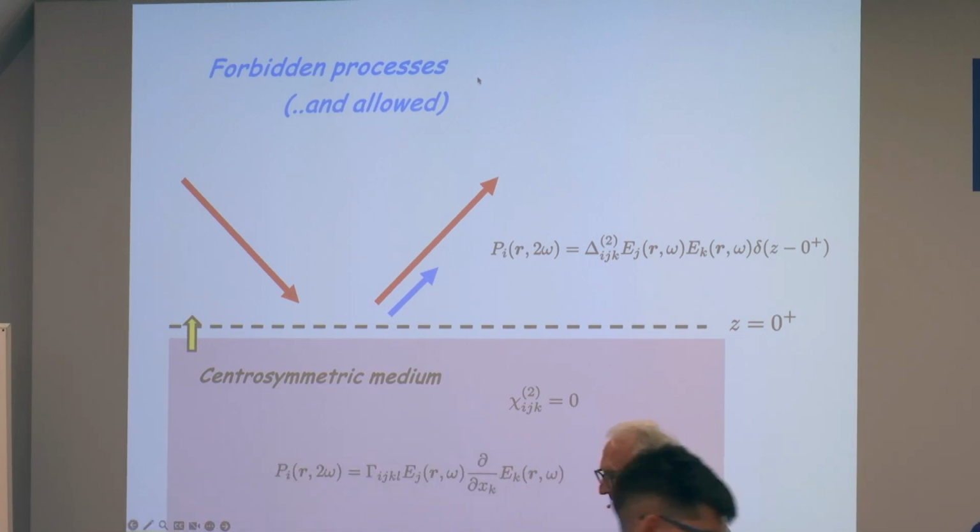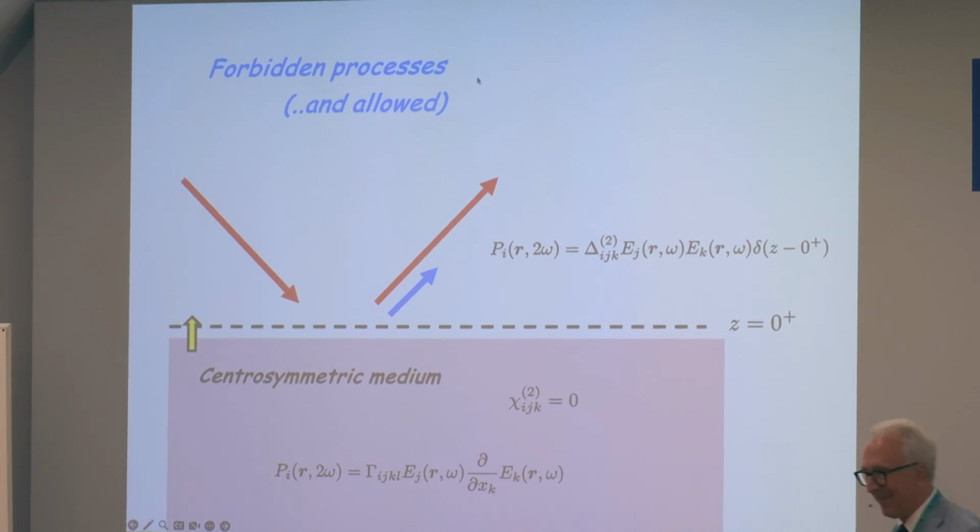But when you say the surface, how deep can you go in the surface to get the second harmonic? In practice, when this effect is large, you're also getting some absorption in the medium, so it's going to go about a fraction of a wavelength in. But the amount of forbidden SHG generated in about a wavelength is roughly comparable to the amount of allowed second harmonic generation done in a couple of angstroms. So the signal from the forbidden and allowed second harmonic generation here are comparable.